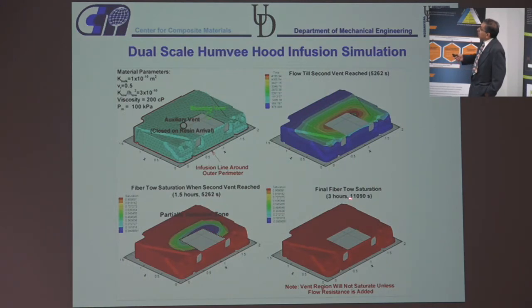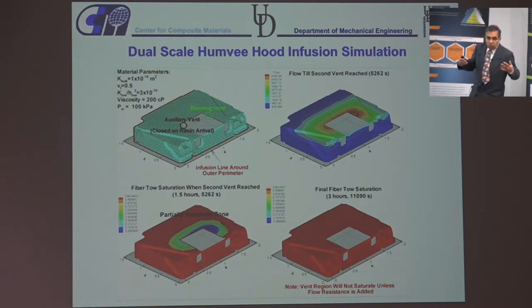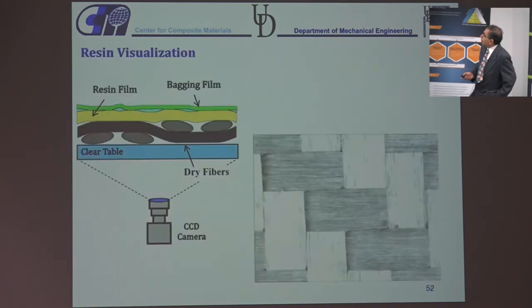And then I have to continue the simulation for another hour and a half to make sure that that other region gets filled. Okay, so obviously it took twice the amount of time, and I wasted some resin, but I was able to saturate the complete thing. Now we also came up with a way to reduce this time, but what you do is at the vent you put in some resistors so that you make the vent very small, so you build up the pressure near the vent, which will allow the resin to go into the tows much faster, and then you can also model that and show how you can reduce that time.